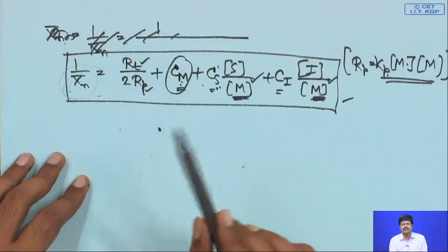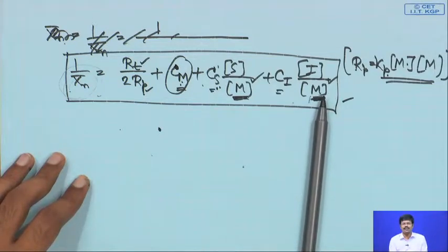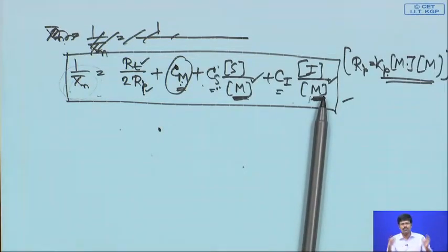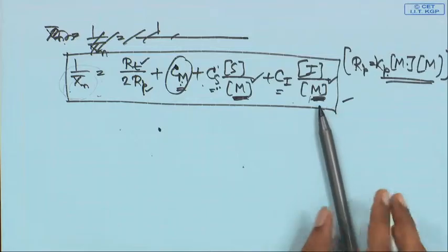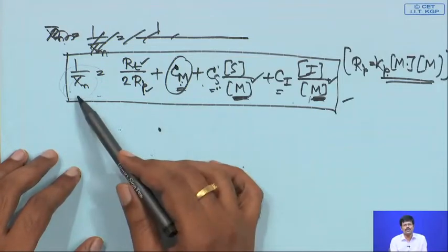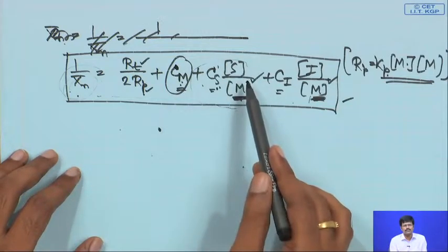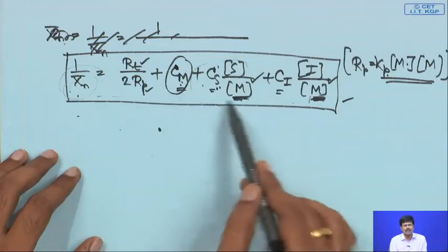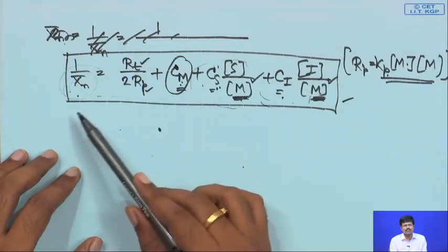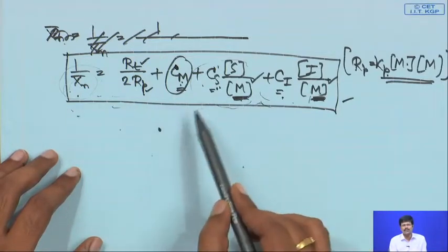These chain transfer reactions are stopping growing chains, so they are limiting your molecular weight. If there were fewer chain transfer reactions, the chains would grow more and the molecular weight would become higher. If there is more chain transfer, your molecular weight can be limited. This may be detrimental when you want to obtain a high molecular weight. Say you have chain transfer to a solvent, which limits your molecular weight, or chain transfer to the initiator that you are using, which limits your x n bar. So, these things are detrimental to your objective.